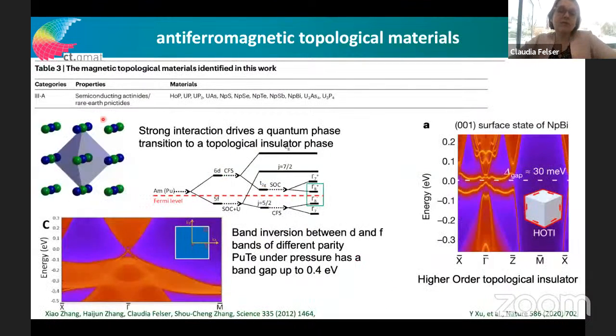So we very early worked on another class of material at the time, in 2012 with Shou-Cheng Zhang, while we were looking for new topological insulators, and one potential candidate, plutonium telluride with the sodium chloride structure. Here's the sodium chloride structure, which shows this interesting band inversion, which I explained at the beginning. So it's an inversion here between the 6d states and the 5f states.